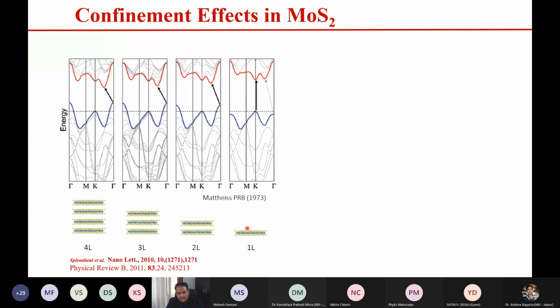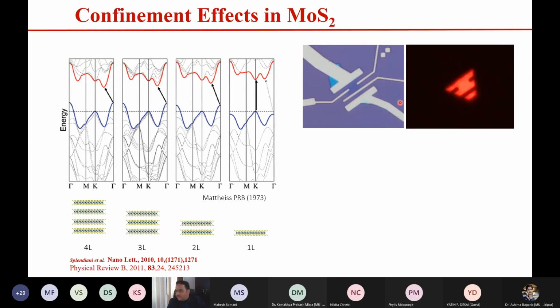If you have a single layer of MoS2, one molybdenum at the center sandwiched between the 2 sulfur, you have a direct band gap. So what it becomes is a direct band gap material. And once you have a direct band gap material, it has very, very interesting optical properties, which include strong photoluminescence from the material. So this is the device on WS2, which is tungsten disulfide. Okay, and you can see here the fluorescent image. You cannot see anything other than the monolayer, and the glow is so large actually.